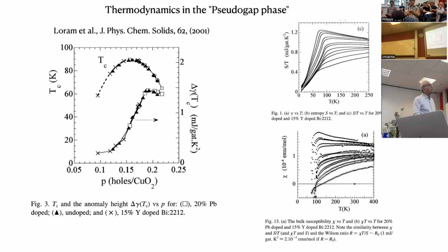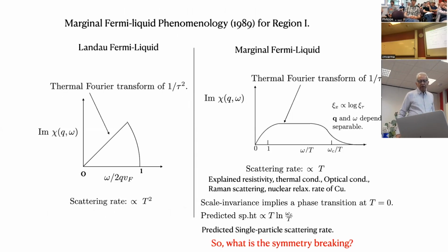And let me again say that if you look at something like that and integrate, you see, specific heat is the derivative of energy with respect to temperature, so you can integrate the specific heat and get out the energy change, and that energy change in this range is significantly larger than the superconducting change. Okay, so very early on, by looking at all these different properties, some colleagues of mine and I suggested, this suggestion was already made by Anderson, that this could not be a Fermi liquid, and we suggested a remedy. What is happening instead of a Fermi liquid?